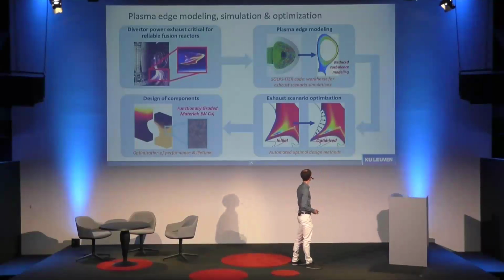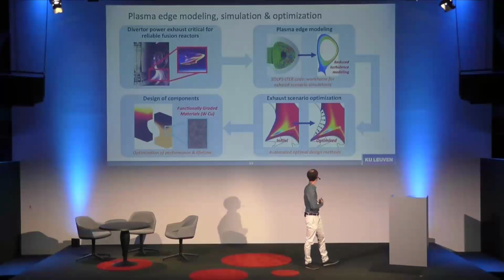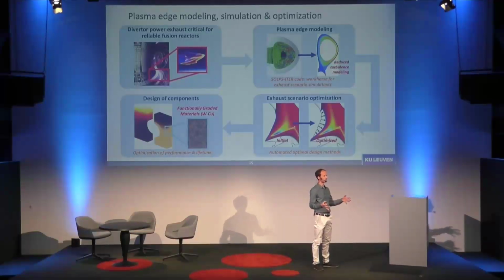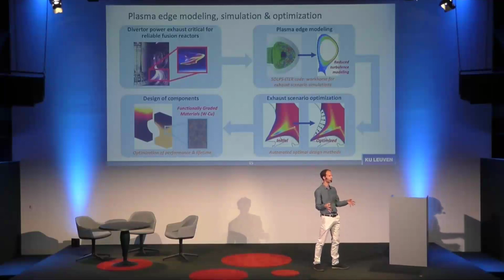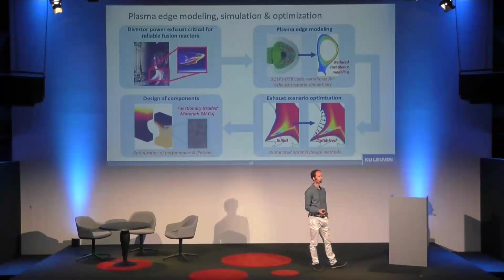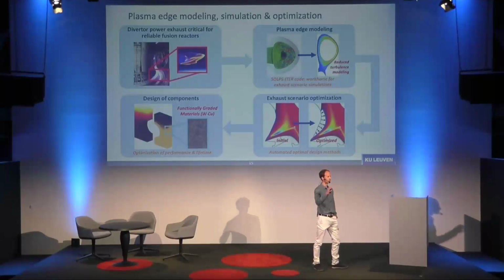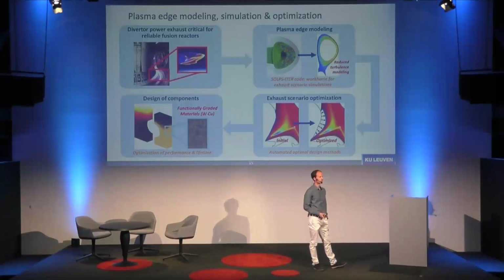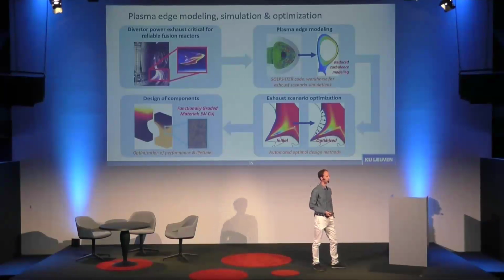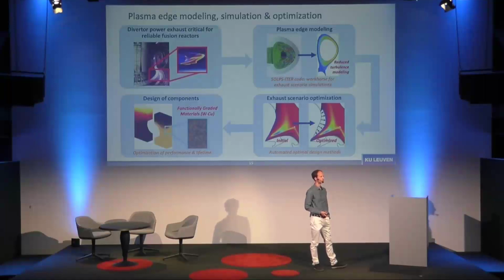Yeah, so very good question indeed. These codes would in principle allow you to, let's say, model where the plasma would strike the tungsten targets. Then if you have estimates of the erosion rates, we can then predict how this tungsten will travel possibly upwards towards the core and whether or not, and under which conditions it would form a radiating mantle or would penetrate, leading to unacceptable impurity contamination of the core. Yeah. So this is indeed what this kind of codes are used for.